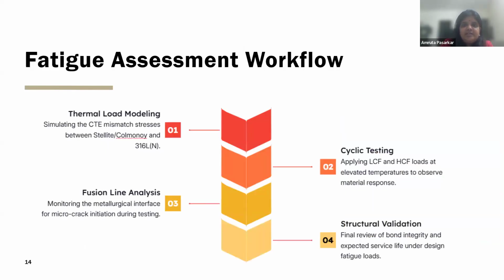Now, how this fatigue testing is done is we can simulate the thermal loading, the CTE, that is the thermal expansion coefficient. The stresses can be simulated between the alloys and the base metal. Then the fusion line analysis, the metallurgical analysis, is done by the microstructures. Microstructure analysis can be done, which I had shown previously, to understand if there are any micro cracks in the interface. Then the cyclic testing is done using low cycle fatigue or high cycle fatigue loads as per the applications and as per the requirement.